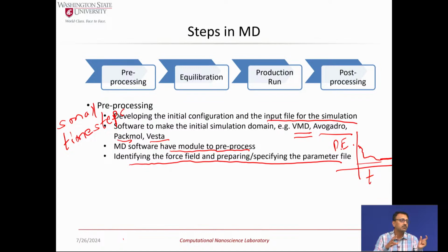Okay? It's smaller than what it should be or bigger than what it should be. So you want to relax the system to the right lattice parameter to get the right properties. And so, a static minimization can do that sometimes. But then there is also dynamic, like a proper MD simulation that you can run for several picoseconds, hundreds of picoseconds, nanoseconds, depends on your system.